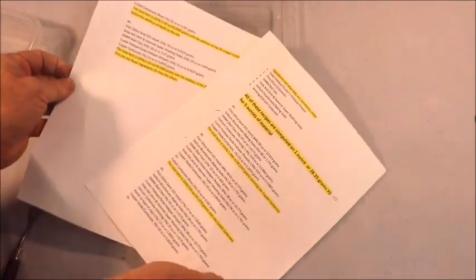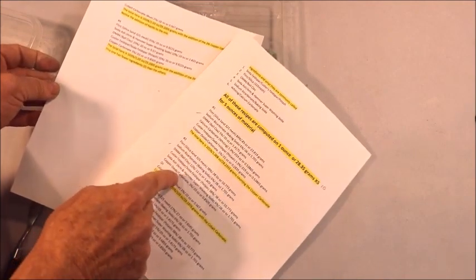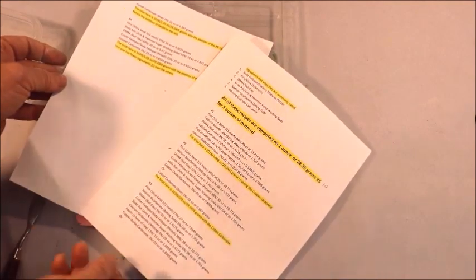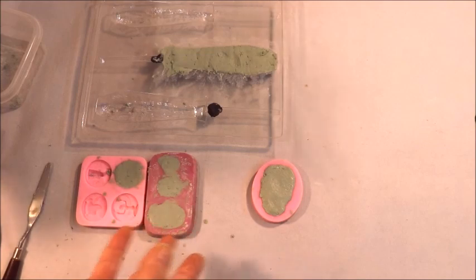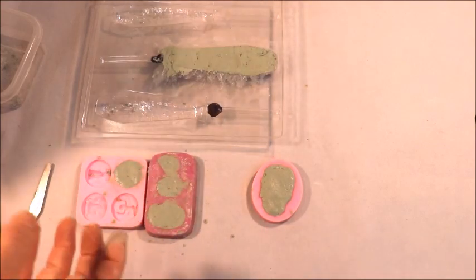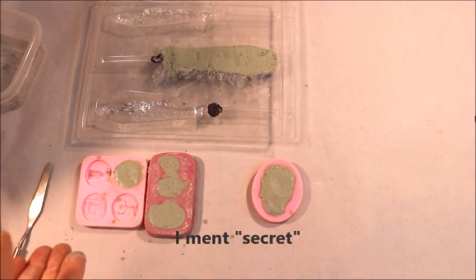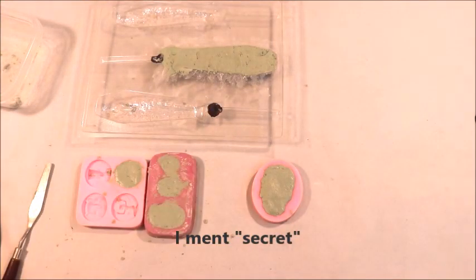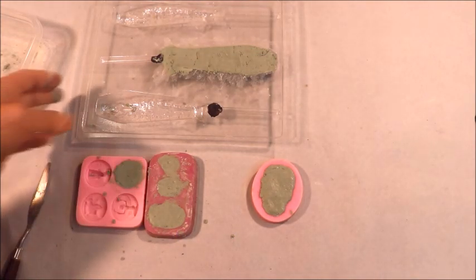But I have here 4 recipes, and we use this number 2 recipe, and it differs from all the other 4 in that it has a higher concentrate of bicarbonate of soda, or a soda salt, or something like that. And I think that's the secret. It also doesn't have any whiting in it. Whiting is nothing but chalk or limestone, but some of them call for it. So that's what you do with those.